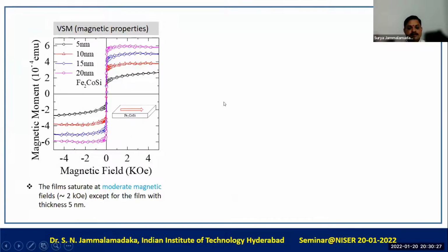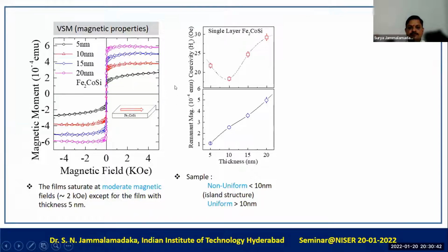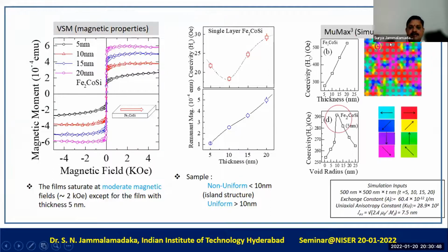So this is the magnetic field versus magnetization graph for the Fe2CoSi thin films. What we do see is a saturation at 2 kilo-oersteds for all the films except for 5 nanometers. This could be due to the fact that the number of grains in the 5 nanometer films is less. And in order to understand this phenomenon, we tried micromagnetic simulations using the MuMax software.